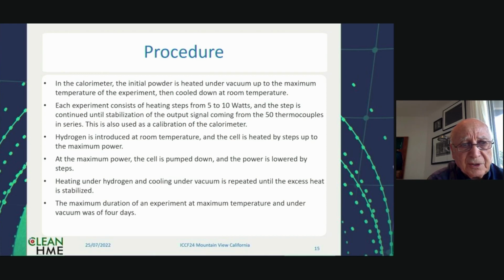In this experiment, the calorimeter is heated by steps of 5 to 10 watts, and the time for stabilization is awaited. It depends, it could be a few hours in order to have complete stabilization, because the inertia of the system is pretty large, so you cannot have instant variation. So we wait for the 50 thermocouples to give a stable signal. Hydrogen is introduced at room temperature, and the cell is heated by steps up to the maximum power. At the maximum power, the cell is pumped down, and the power is lowered by steps again. Heating in hydrogen and cooling under vacuum is repeated until the excess heat is stabilized.